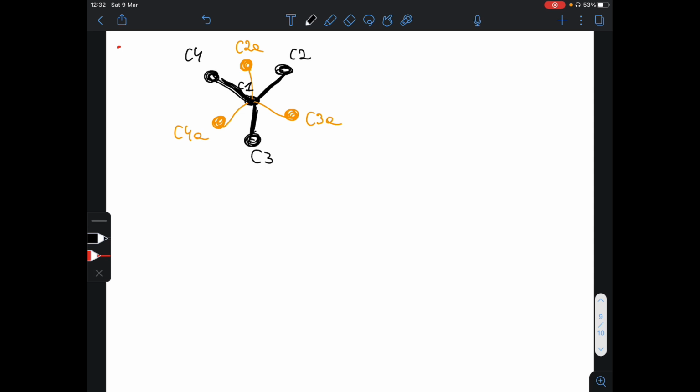Okay, so what are we going to do? We're going to restrain distances first. We're going to restrain 1,2 distances and 1,3 distances within this disordered group. How are we going to do that? Let's start with 1,2 distances. To do that, for now, we will only use SADI restraints. For 1,2 distances, the default value is 0.02. The strength of the restraints, the uncertainty, is 0.02 by default.